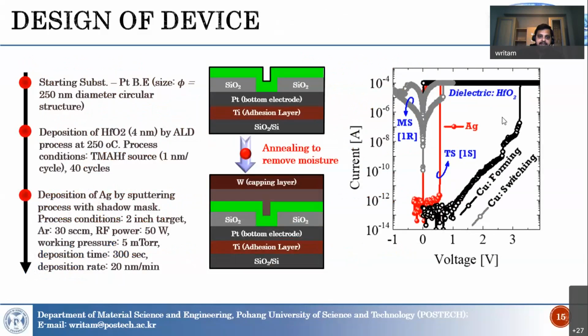Here is a very simple device stack. It is the same stack: you have the Pt bottom, then the hafnium oxide as the switching layer, and then the top electrode layer. Normally the top electrode is silver. In this work, we have used both silver and copper, but the rest of the work will focus only on silver devices, because copper devices mostly show memory switching behavior, while silver devices have the capability to show both behaviors.